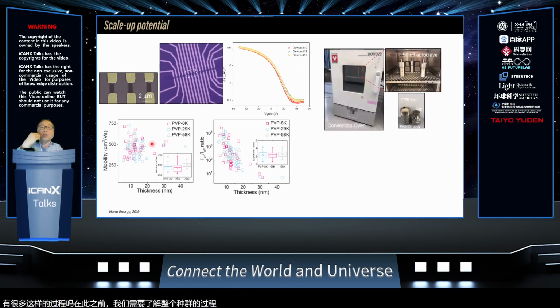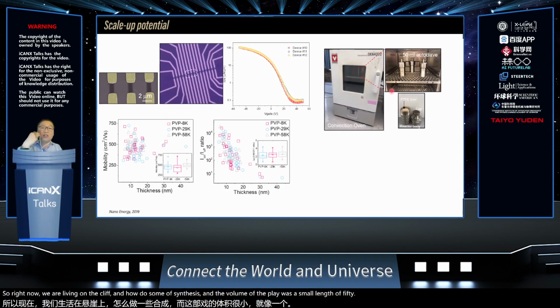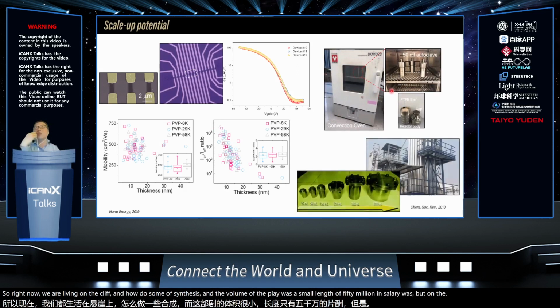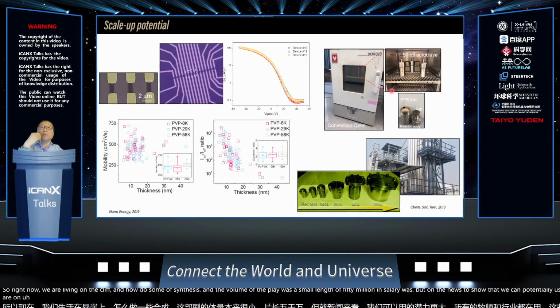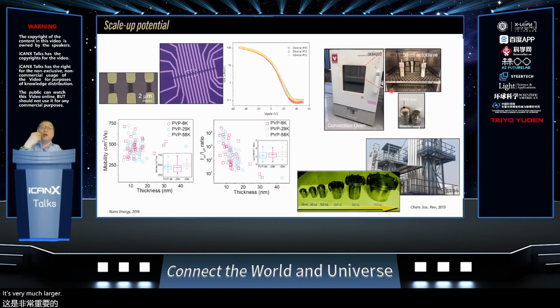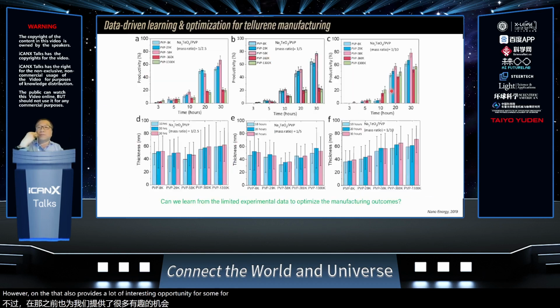Right now we are using autoclaves and hydrothermal synthesis, and the volume of the autoclave is small, like the standard 50 milliliter ones. But the literature shows that we can potentially use even larger autoclaves, and the industry has been using this hydrothermal process at a much larger volume. Of course, it's not trivial to simply scale from what we have been doing in the lab to those industrial settings. However, that also provides a lot of interesting opportunities for us to explore and study.